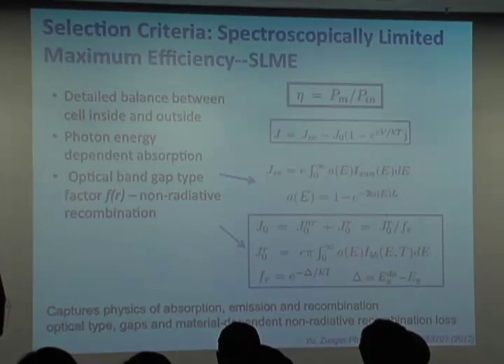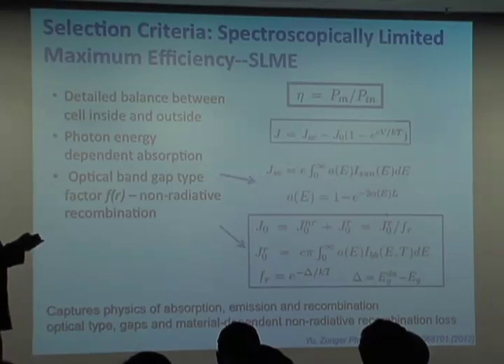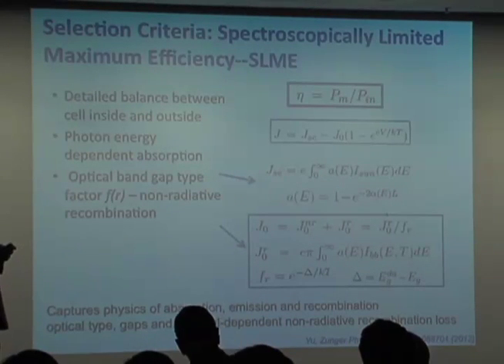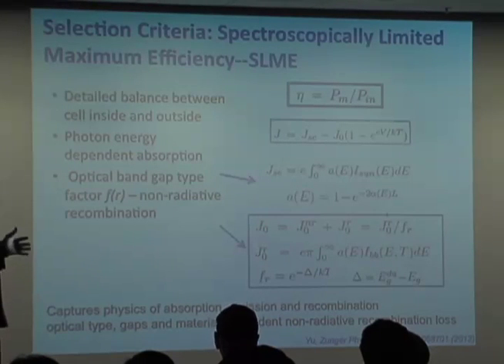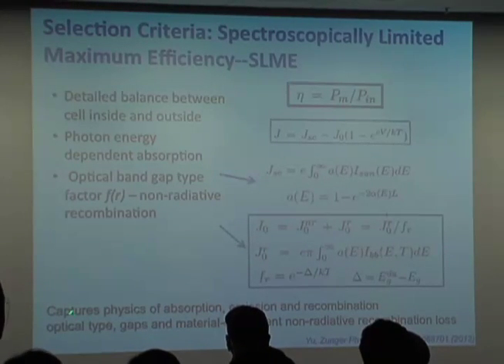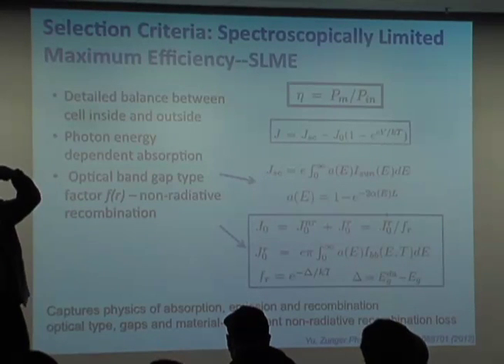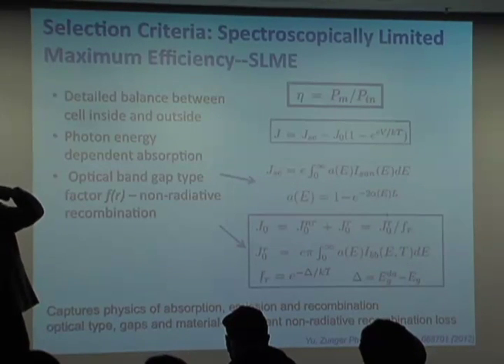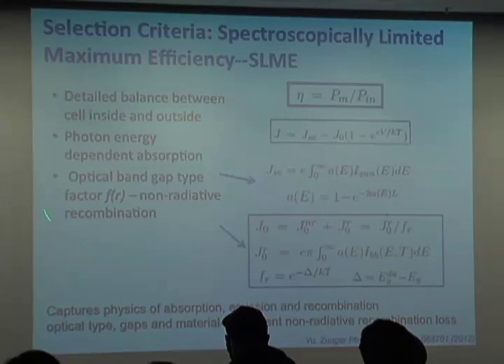And the metric that we actually want to screen against is a selection criteria that Liping Yu and Alex Zunger have developed within our center. And it goes beyond the simple Shockley-Queisser assessment, which just says take a band gap and then assume a lot of things are constant and you can get a maximum efficiency. It actually looks much more at the physics of absorption, emission, and recombination. It looks at the photon energy dependent absorption. And it also looks at this non-radiative recombination for a lot of cases, not just where you have a direct allowed transition, but maybe you have an indirect allowed transition or a direct unallowed transition below that direct one, and the recombination rates can be very different.